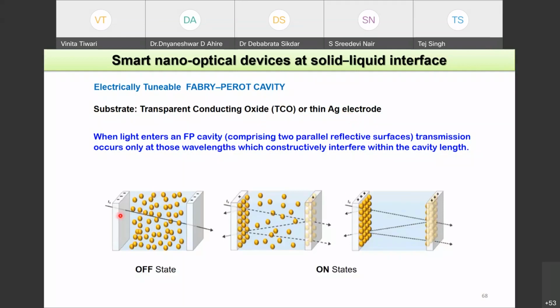So if nanoparticles are again negatively charged, and this is a water-filled cavity, and these are the cavity walls. So when the cavity walls, these are made of TCO, transparent conducting oxide, like ITO, or you can make them with thin silver electrode. So when they are negatively charged, nanoparticles are not attracted, they are dispersed in the aqueous medium. So they will simply allow the light to pass through. Okay, so that is like the resonance cavity is off. It is not existing. It is not doing anything to the existing light. Maybe somebody can argue that what if some nanoparticles come in the path of the light? Yes, there will be slight scattering and slight absorption, but that will be really minimal.